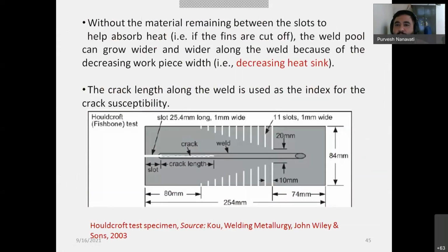So now, the material remaining between the two slots helps absorb the heat. This is something I have mentioned to you. The crack length along the weld is used as the index for the crack susceptibility. Now, whatever the crack length you examine over here, right, from where you start. So initially some slot will be cut to facilitate the crack tip to propagate. This is a process fundamental, or this is a standard procedure.